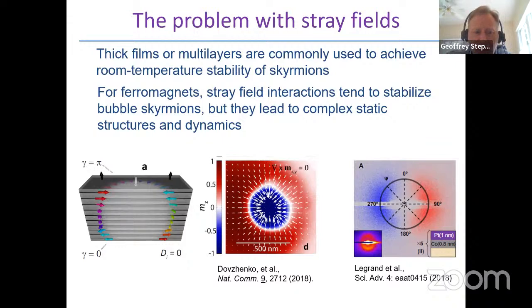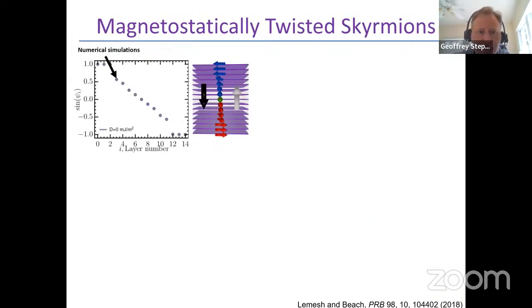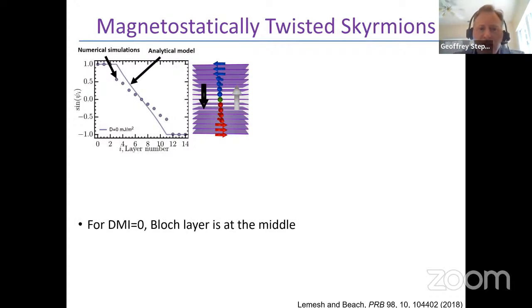magnetic skyrmion in a multilayer, Néel kinds of textures where the handedness of the Néel structure on the bottom of the stack versus the top of the stack is inverted because of closure stray fields that go through the thickness of the film. And this has been observed by NV magnetometry and X-ray imaging in these kinds of structures. And we can understand that, and we've shown in the PRB article referenced at the bottom here, that the stray fields actually mathematically appear as something that looks like a DMI.